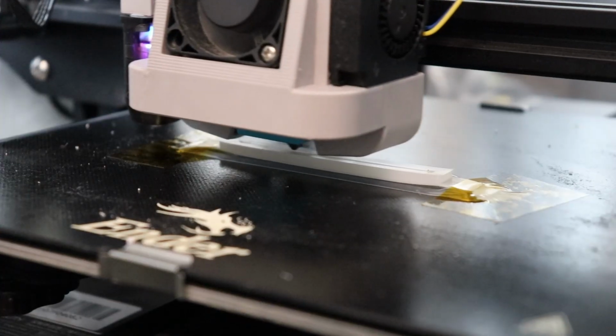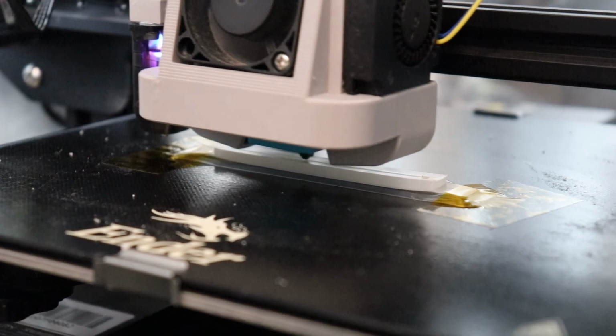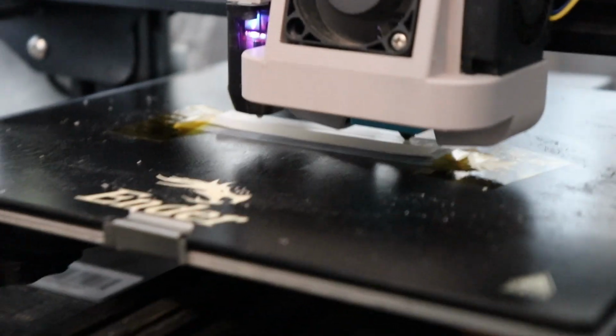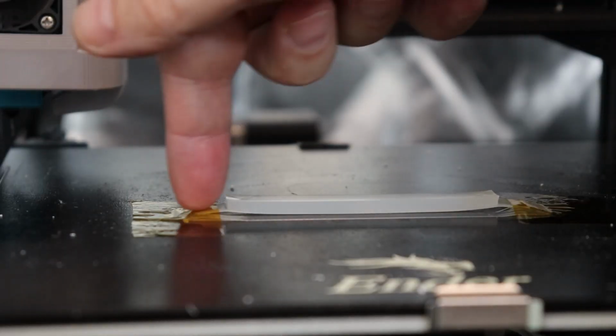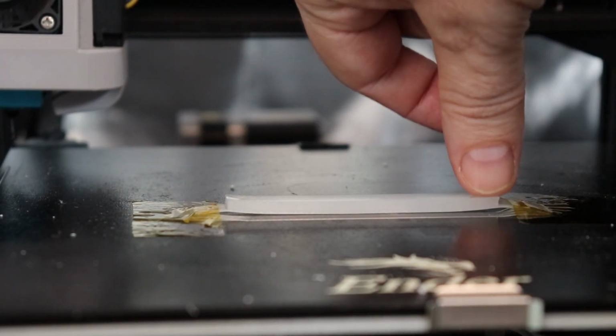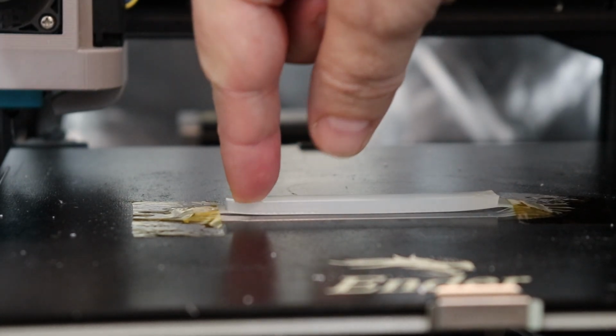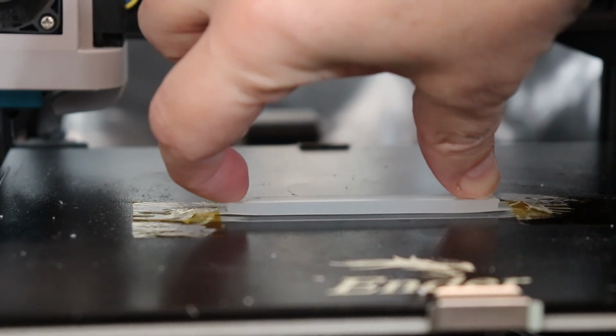The first test specimen printing is almost finished. Even with the Kapton tape it is very hard to hold it down. And the temperature inside the enclosure is 46 degrees Celsius. And you can see even with the Kapton tape it was very hard to hold it down. So definitely not a problem with the adhesion.